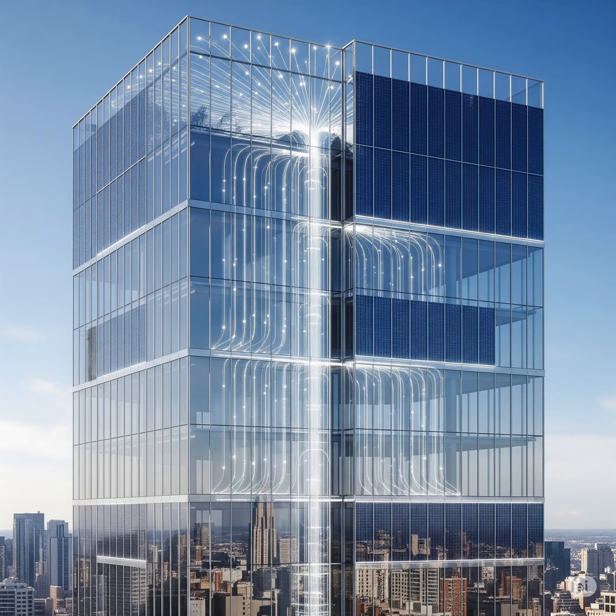So what kind of numbers did they achieve with these optimized panels, the ones with the moth-eye structures? The results are really impressive. They achieved an LUE of 4.67. And how does that stack up? Well, that came from having an average visible transmittance, AVT, of about 56.45%, so over half the visible light gets through, and a PCE of about 8.28%.